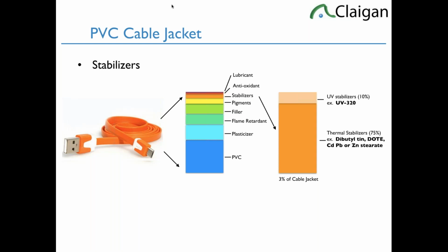So especially as we get to cheap plastics, like your dollar store type plastics, we get cadmium failures all the time. Cadmium in particular is a very good stabilizer for transparent PVC. We find it in other things, but in transparent PVC, it's an excellent stabilizer. And so for cheap plastic, we see cadmium in transparent PVC all the time. And it could just be the clamshell, actually. It's very, very common. Lead we see in PVC a lot.